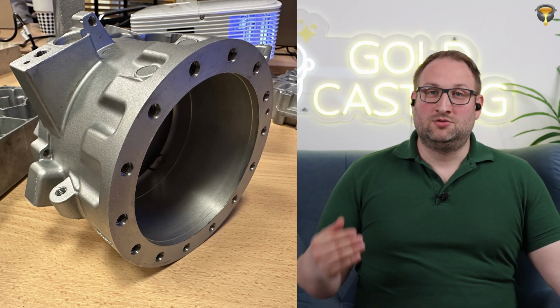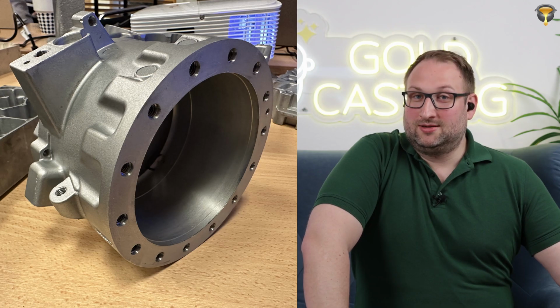And there is no way that high-pressure die casting with its turbulent fill can hold that pressure. Impossible. Even with impregnation, it doesn't work. And you can't even impregnate these things because they have to be welded shut. But Rheocasting, without impregnation, perfect laminar fill, that thing is leak tight, tested at 180 bar helium level tightness. Ideal thing. These run in hundreds of thousands of pieces per year. Perfect to get new business in, even with high volume production. And I think that shows you how extreme the applications can be for Rheocasting.